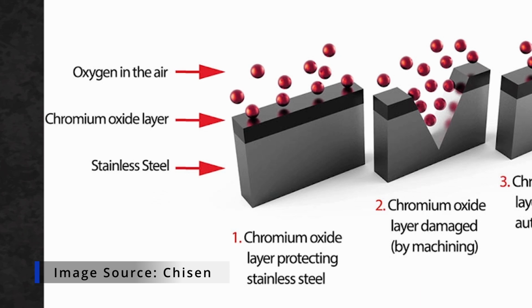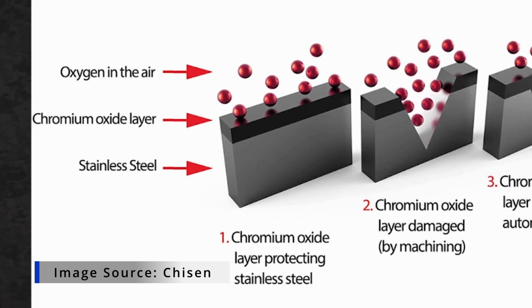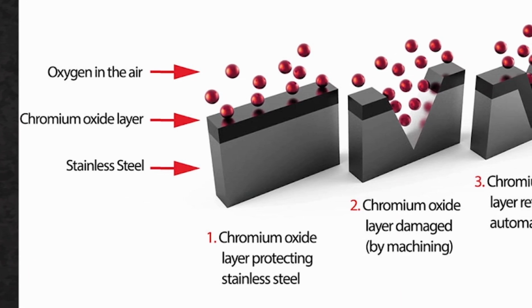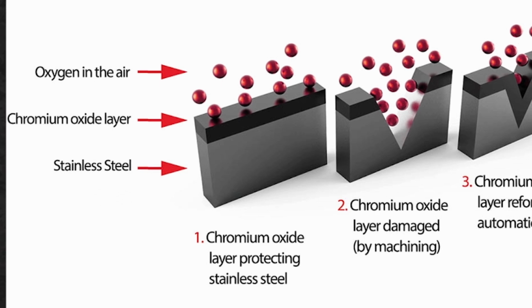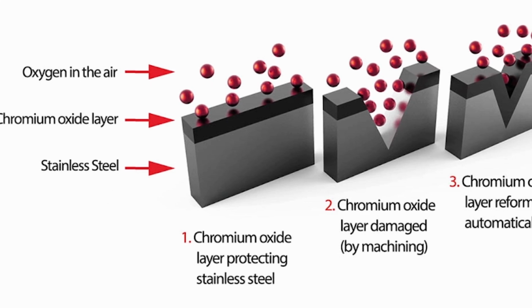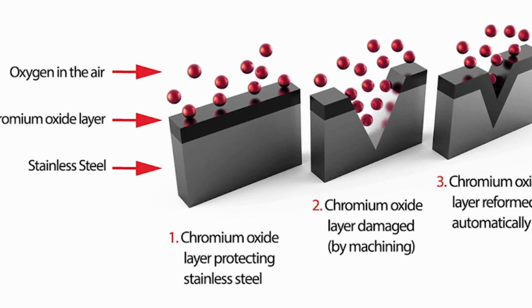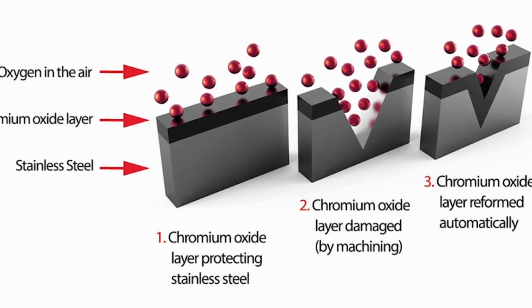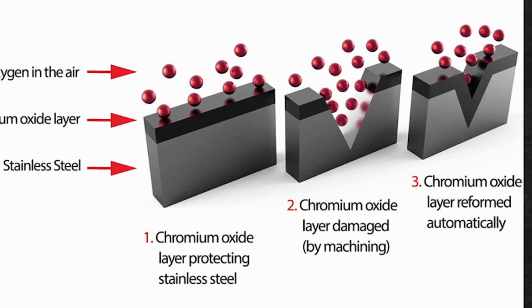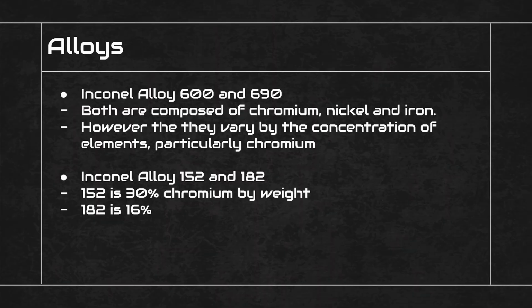When chromium metal interacts with oxygen in the air, it forms a chromium oxide layer. This layer protects the rest of the alloy underneath it from the oxygen, thus preventing oxidation. Now, when that metal gets kinked or the chromium oxide layer is damaged, it can then repair itself and reform that layer. The more chromium you have in your alloy, the better it is at doing this. Therefore, Inconel alloy 690 was preferred over 600.